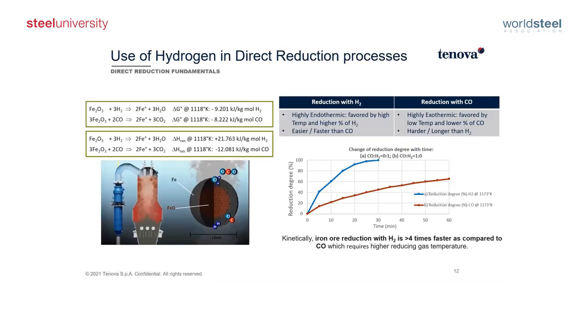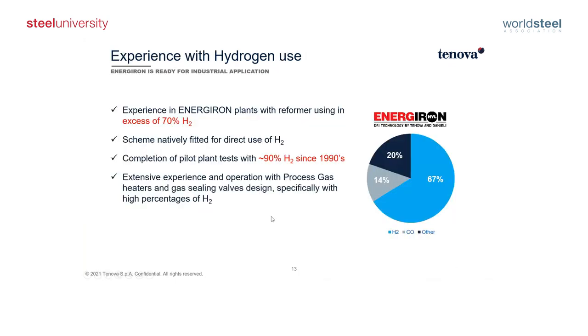Actually, we have been doing tests with a high hydrogen concentration in the module since the 90s. And we measured the kinetics of the reaction of iron reduction by using various concentrations of hydrogen. So, for instance, we know that the reduction by hydrogen is highly endothermic, so it's favored by having high temperature in the module. But we also know that the kinetics of reaction, mostly due to the higher diffusivity of the hydrogen atoms into the pellets, proceed four times faster than the reduction by carbon monoxide. So actually a module designed to work with methane, when you feed it with a higher percentage of hydrogen or entirely hydrogen, becomes more productive due to the quicker reaction of reduction inside the module.